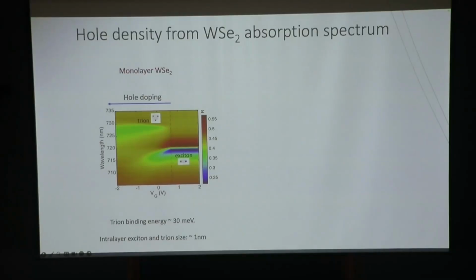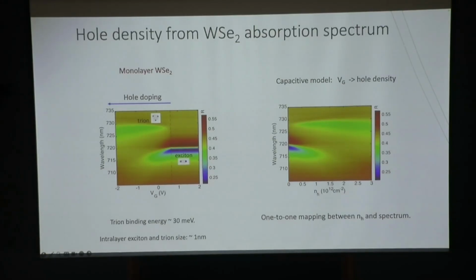Then when you apply gate voltage, which will attract holes into the layer, you basically have hole doping, just like a field effect transistor. You can see the spectrum start to change. The exciton resonance becomes weaker and shifted, and a new peak appears. That corresponds to a trion: the exciton is bound to another hole, inside the monolayer itself. This is known as the intralayer trion. We can convert the gate voltage into the carrier doping by using a capacitance model. So you can see the optical spectrum changing at different carrier densities, and there's a one-to-one mapping between them.